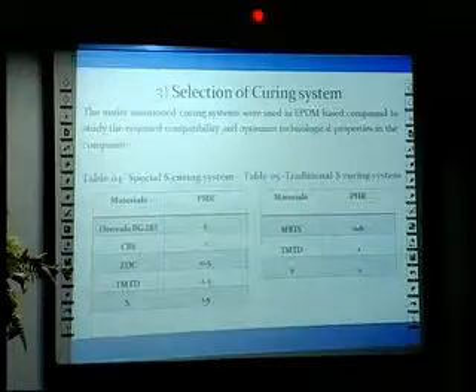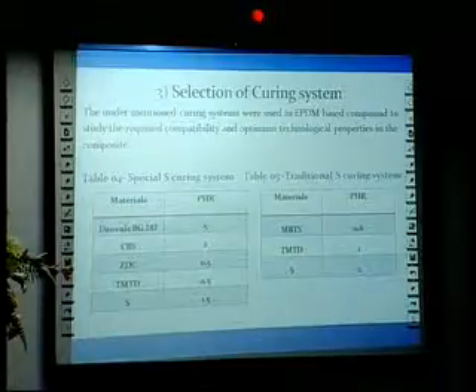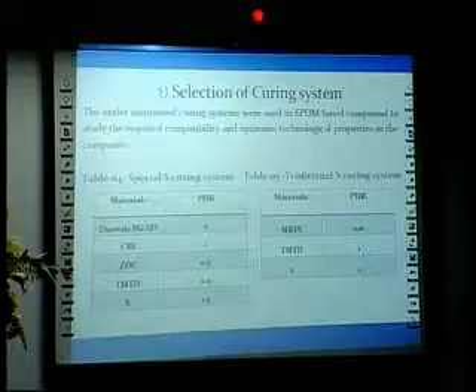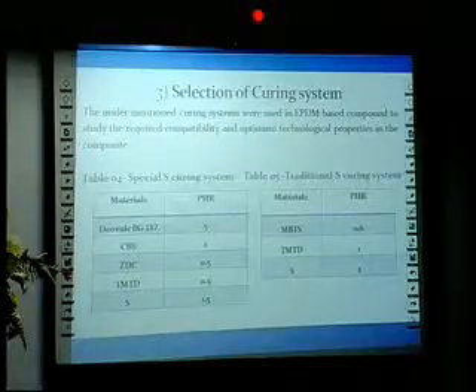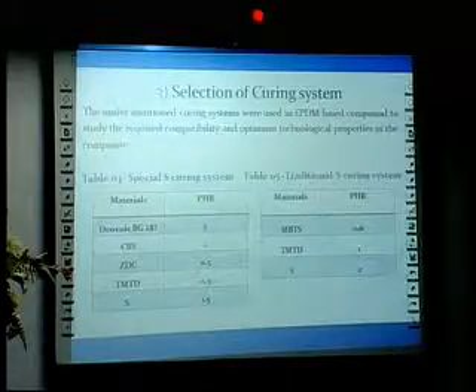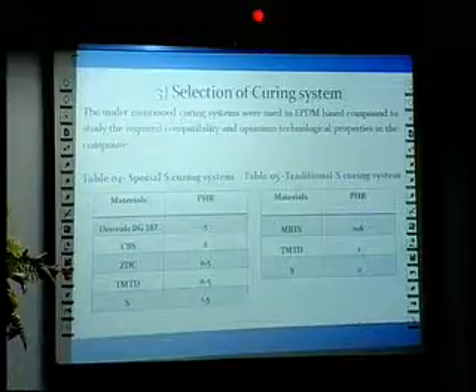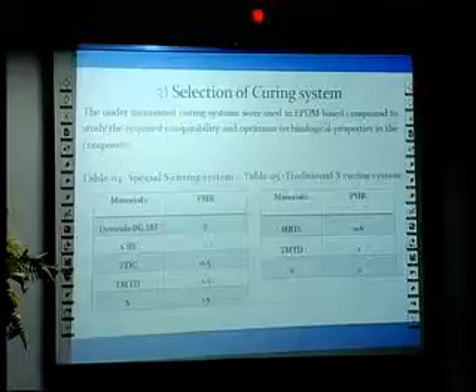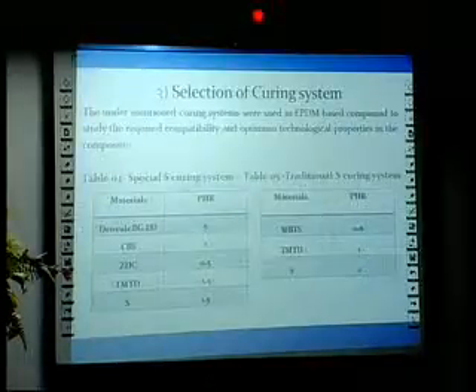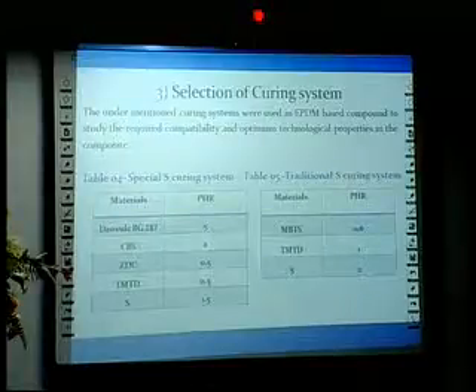The third part of the experiment is the selection of the curing system. My main idea is to develop the EPDM/NR-based vulcanizate. So the EPDM rubber needs a sulfur curing system. The curing systems illustrated in Table 4 and Table 5 were used in the EPDM-based compound to study the required compatibility and adherence with the natural rubber compound, and also to get optimum technological properties in the composite.